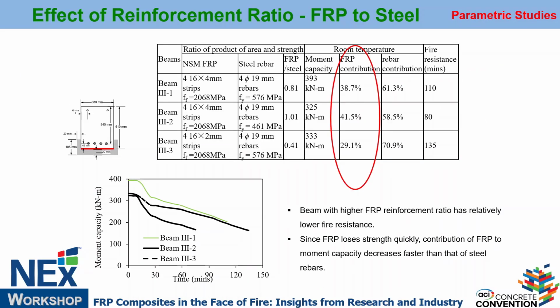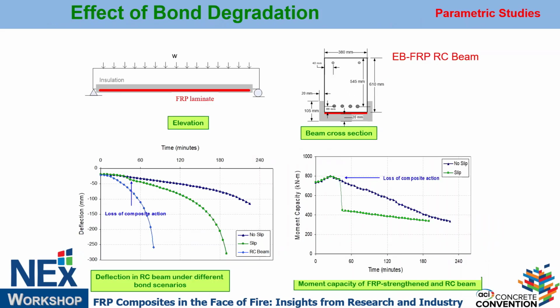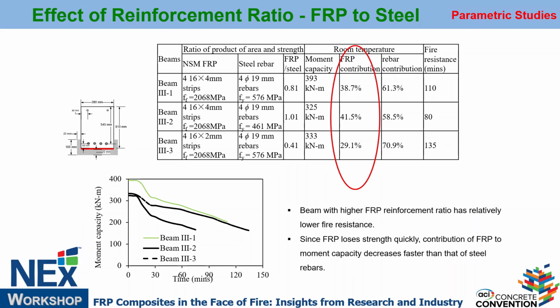Now, what about how much you strengthen? A lot of times material cost is not that much. So what happens is, the more the FRP contributes as part of strengthening, the worse it is from the fire point of view. So the lesser the contribution of FRP, if it is 29.1% contribution of FRP in this case, it will last 135 minutes. But if the contribution of FRP is 40% plus, then it can fail in 80 minutes. So, unnecessarily don't strengthen it too much. Okay, you can take that measure.